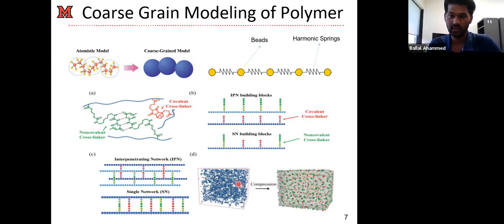The packing is done, yeah, okay. I just told that the packing is done just by compressing your simulation box, right? So you know how much polymer is there, I mean, how many polymer chains there are. You know their mass, and you know the shape and size of your simulation box, and you start compressing it, then you know at what volume you will reach the desired density. So it is just a simple calculation of how much you need to reduce the XYZ dimensions in order to reach that volume fraction. That's how, by compressing the box, we reach the desired density.